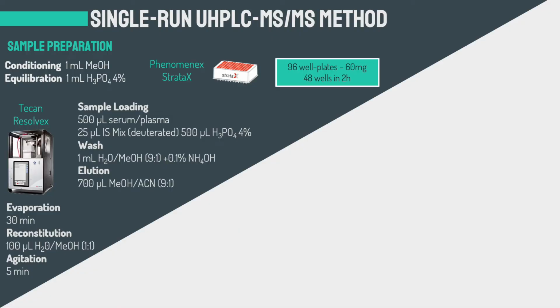In the final method, the sample preparation procedure has an utmost importance. Indeed, sample cleanup protocol should be capable at the same time of extracting all target analytes, which own strong differences in terms of polarity, and reducing matrix effects as much as possible. For this aim, we chose a solid phase extraction using the 96 well plate format. The extraction protocol starts from 500 microliters of serum or plasma, and it is capable of extracting all target steroids with a recovery higher than 80% coupled to negligible matrix effect. The whole procedure takes 2 hours to process 48 samples and could also be partially automated.